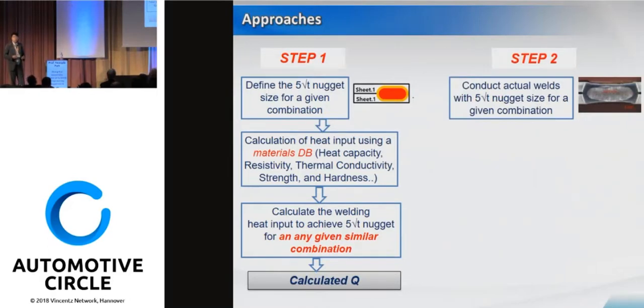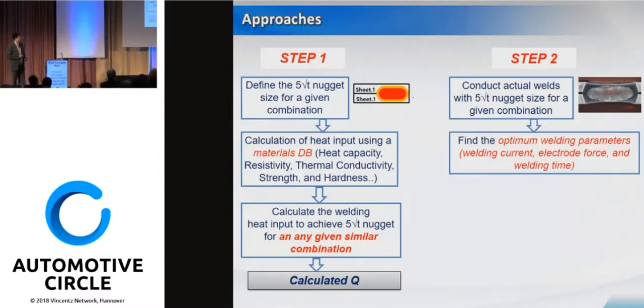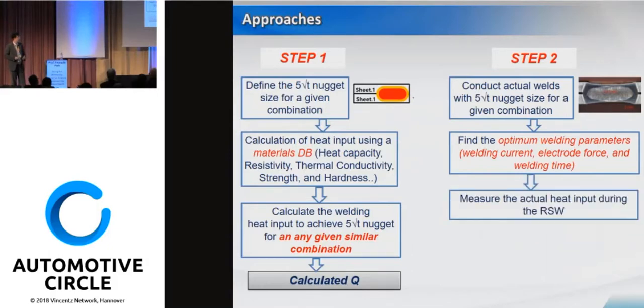From here, not the calculation, I do the actual test. Conduct the actual weld which possesses the 5√t nugget diameter for a given combination. So I find the optimal welding parameters to have this 5√t nugget diameter, for a specific optimized welding current, force, and welding time. And then I measure the actual heat input during the resistance spot welding here. So I do have a measured heat input in here.